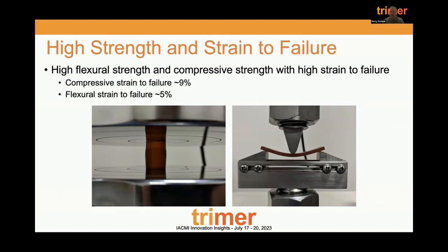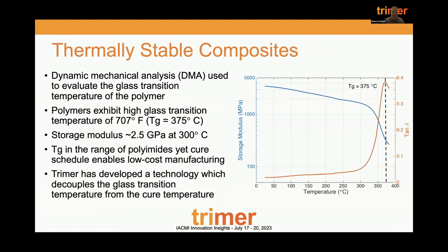On the left, I have a compression specimen at 9% strain prior to failure. On the right, we have a flexural specimen at 5% strain to failure, or 5% strain. At that point, the ASTM is actually invalid. So you can get very good compliance out of these materials and maintain that high strength and stiffness.